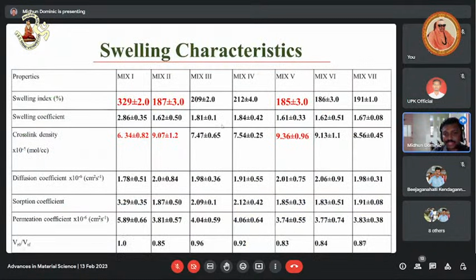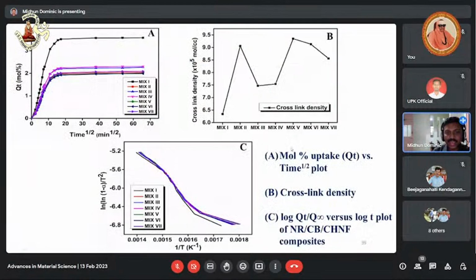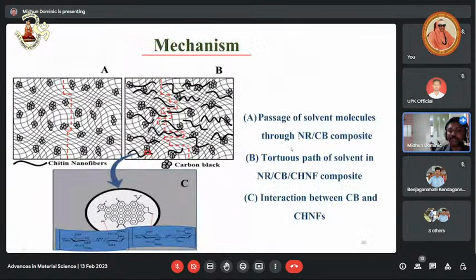And regarding swelling index, we have conducted the swelling characteristics in toluene. Here it is 187 and here it is 185. That is, swelling index is decreased and cross-link density is improved from 9.07 to 9.36. And we have proposed a mechanism. This might be the mechanism.